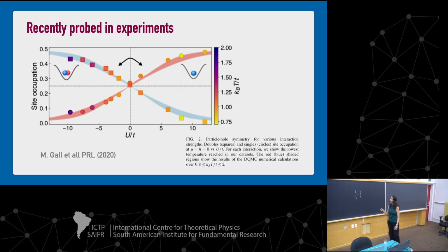So this change, this mapping of the attractive into the repulsive model, has been probed in experiments. This is a paper from 2020. This is the attractive part, and this is the repulsive part. And you can see they map pretty much on each other. And here, the circles are the singles, and the squares are the doubles. So we map the doubles in the attractive case to the singles in the repulsive case, and the other way round. So these things map onto each other.